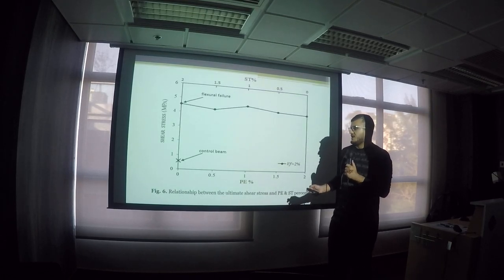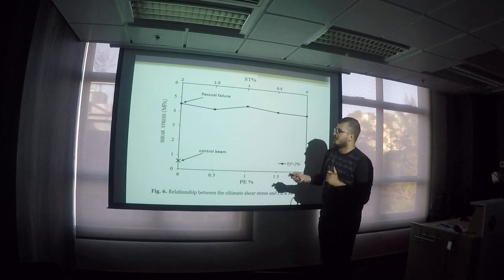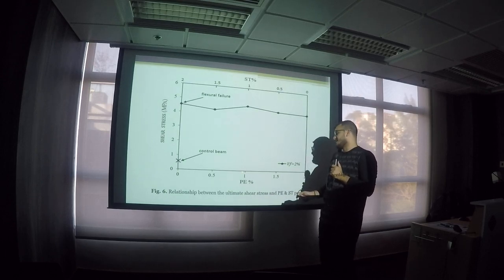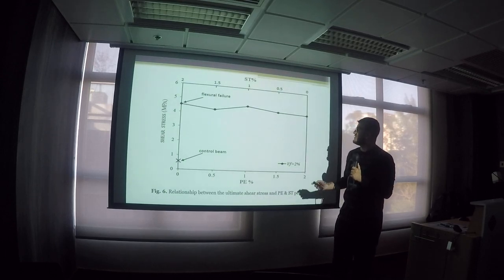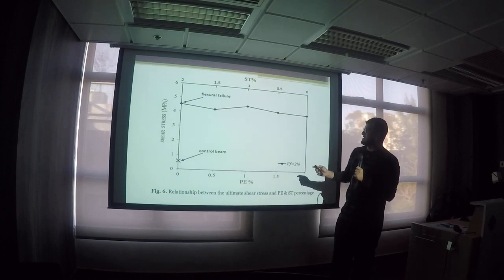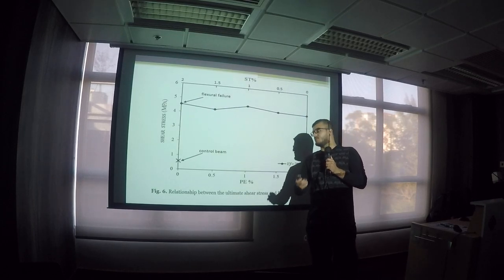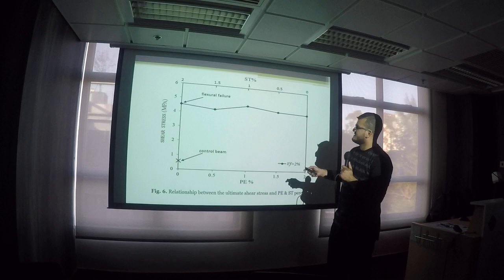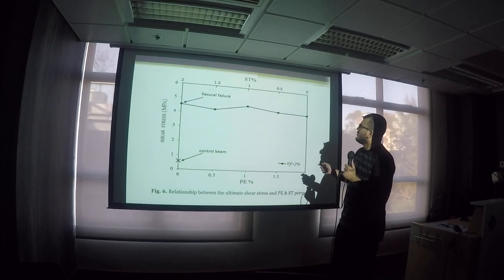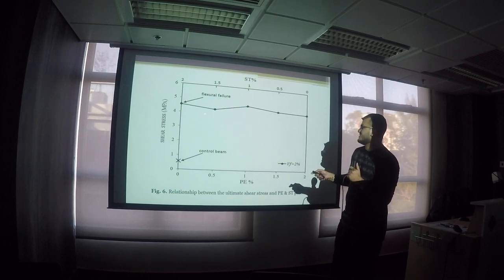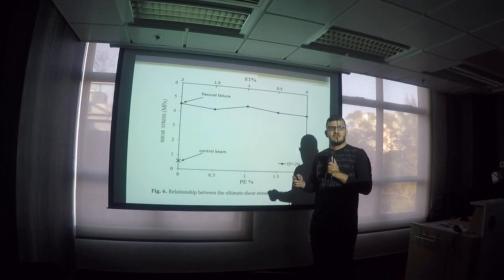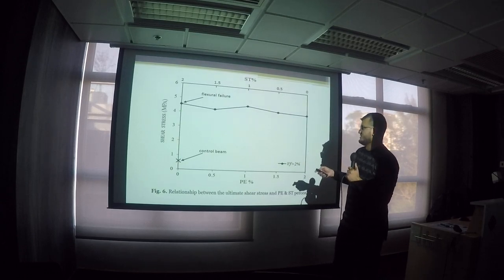Now, we are studying the shear behavior. So, when I plot the shear stress against the hybridization ratio, which is the polyethylene and the steel, for example, at this point it means that we have 1% steel and 1% polyethylene, as I said, because the total volume is 2%. So here, as you can see for the shear stress, we didn't notice any trend because all the hybrid beams have approximately the same shear strength relative to each other.